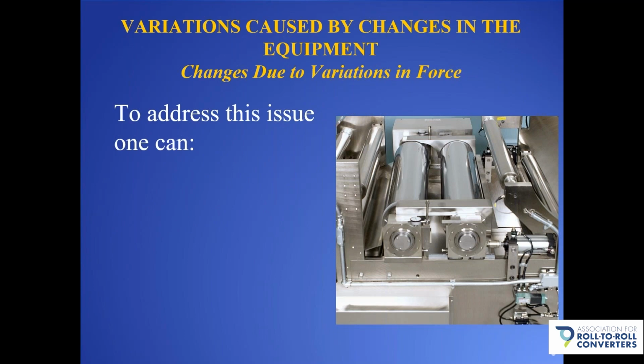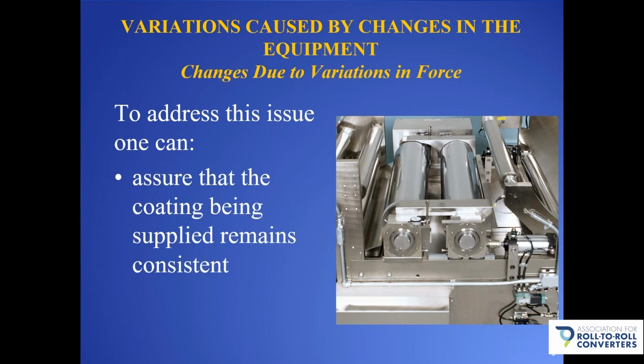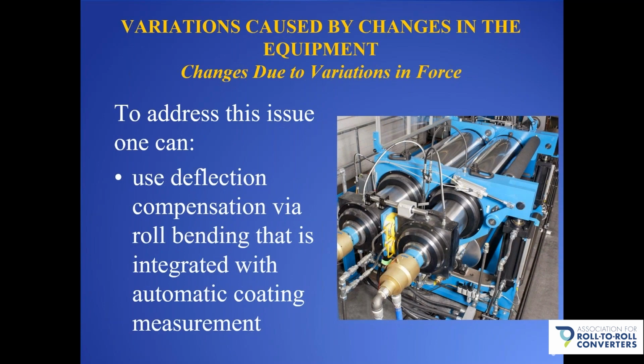So how does one address this issue? Well, first of all, assure that the coating being supplied remains consistent. Assure that the coater's operating parameters remain consistent throughout the run. And lastly, you can get very complicated, and as shown here, you can use deflection compensation via roll bending that's integrated with an automatic measuring system and therefore automatically adjusts for any changes in the roll deflection.